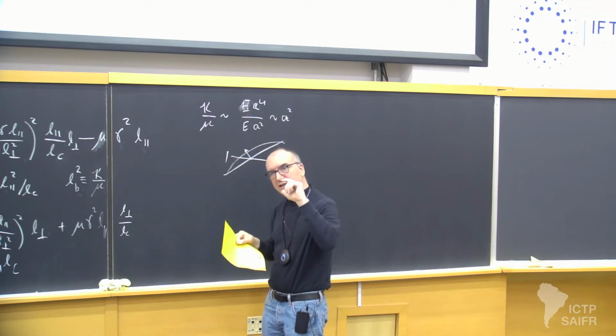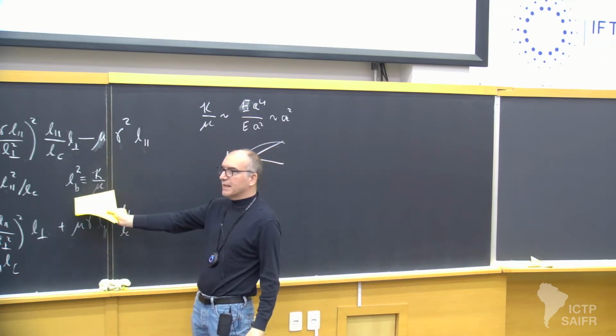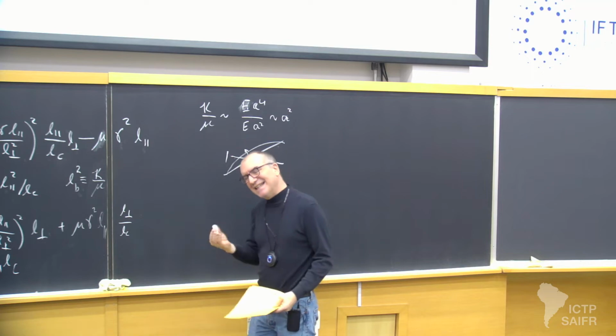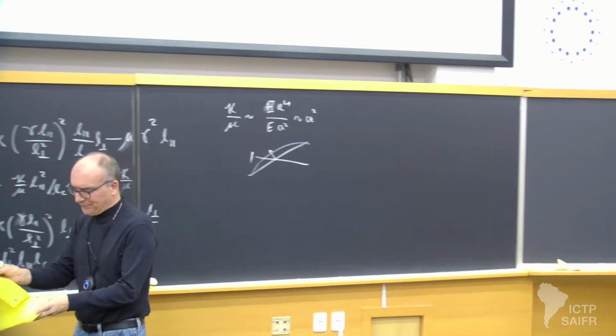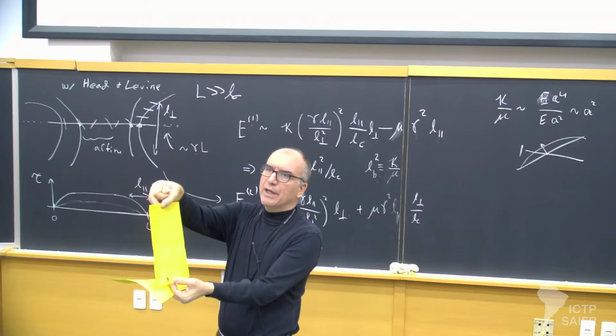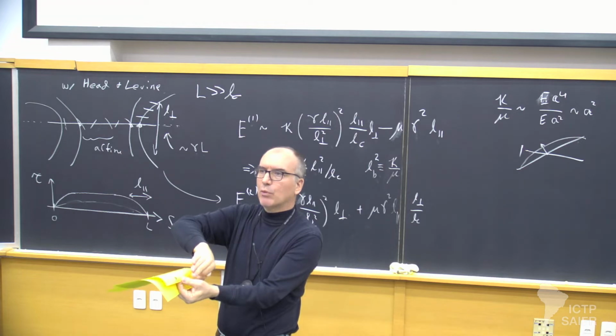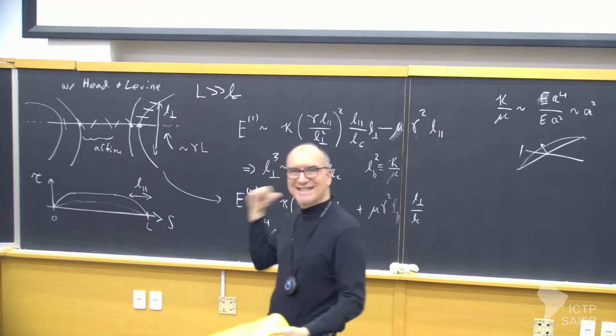And so if I take the ratio of the two, because of the different units, I get a length squared, so I can define that as the bending length. This is actually something going back to Euler. If you ask the question, if I pin the boundary condition of a fiber at one end, and I put an arbitrary force on the other end, over what range does a bend occur? It's that length.